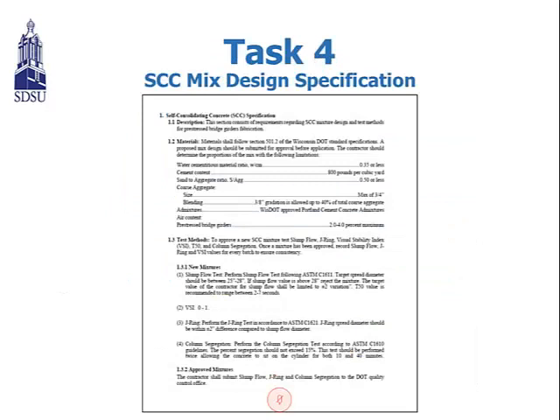And based on the analysis of the data and the feedback from the technical project panel, we established SCC mixture design specifications. So for example, for the self-consolidating concrete specification materials, the water cement ratio is 0.35 or less, and the cement content is 800 pounds per cubic yard, and sand to aggregate ratio is 0.5 or less. And coarse aggregate size is a maximum of 3/4 inches, and blending is allowed with 3/8 inches, gradation allowed at 40% of the total coarse aggregate. And you can see the other details in the mix design specification in this slide.